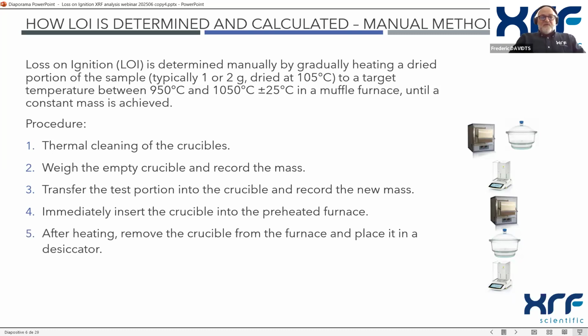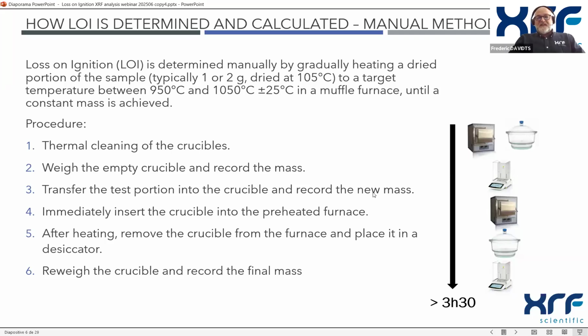Then we remove it again and put it in the desiccator for cooling, to avoid the sample catching moisture, of course. Then we will again reweigh the crucible and record the final mass. So we can see that this process is relatively long and could last more than 3 and a half hours, and even more time in some cases.